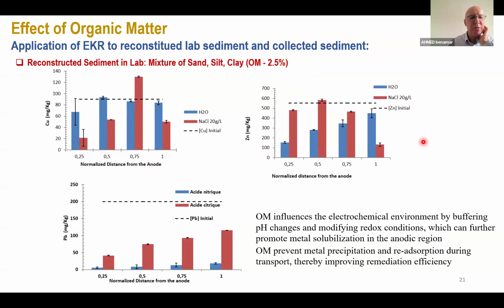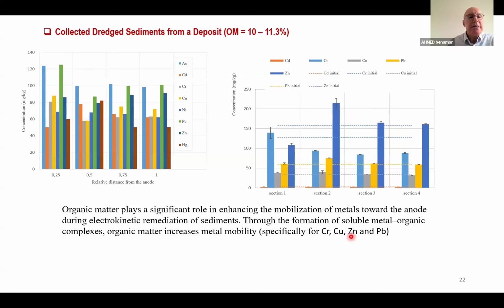So in this case, the metals, mainly two metals here, copper and zinc, are moving according to their charge. So here we see that with citric acid as additive, the lead moves toward the cathode. So the organic matter can influence the electrochemical environment by buffering pH change and modifying redox conditions, which can further promote metal solubilization in the anodic region, and the organic matter can prevent metal precipitation and reabsorption during transport, and then improve remediation efficiency.